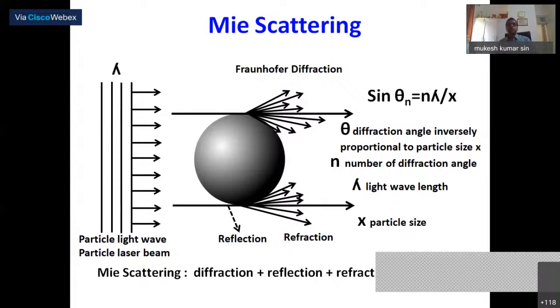This is based on the Fraunhofer diffraction technique. If you see the laser beam, there will be a particle which comes in the way of this laser beam. Then, as per the Fraunhofer diffraction, some part will go direct, some part will reflect, and some refraction will also take place. So this will follow sin theta n = n lambda / x, where theta is the diffraction angle, which is inversely proportional to the particle size x, and n is the order of diffraction, with the angle taken in radians. So this Mie scattering concept is based on diffraction plus reflection and refraction.